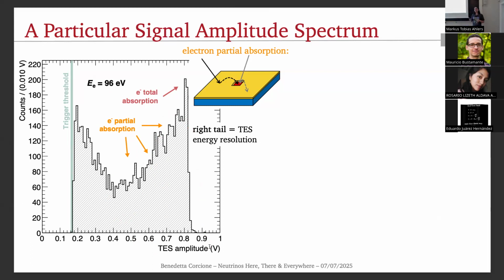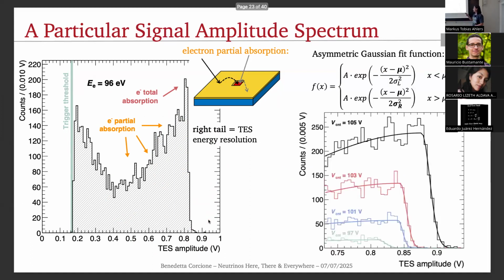But at the electric field and the temperature we are using, we can consider the nanotubes as a monochromatic source. So we directly link the right tail of this peak, so the broadening of this tail, with the TES intrinsic energy resolution for electrons. That's why we decided to study this peak, to fit this full absorption peak, focusing on its right tail, with an asymmetric Gaussian defined with a right and a left standard deviation.